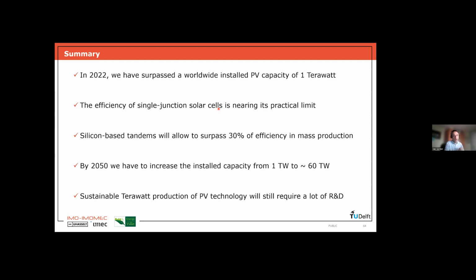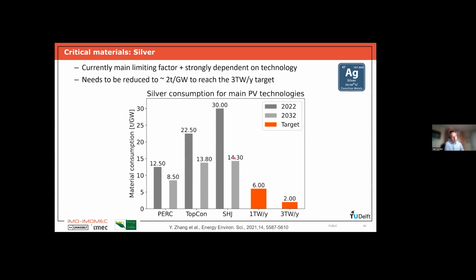Yeah, so that's a good question. But as I've shown in my slides, at the moment, for instance, from the point of view of silver, PERC is actually doing pretty well. And if we compare, because back surface field is not anymore considered in these graphs, because basically it has already faded out. It's really the past. But if we compare aluminium BSF with PERC, I would say the PERC has a much higher efficiency. And because of this, from an environmental point of view, because the cell concepts are pretty similar, so the amount of silver that you need to use and the wafer thickness and so on, it's all very similar. So from an environmental point of view, I think the PERC is for sure going to do much better than the aluminium BSF, because we consider everything from the point of view of how much you need of something and how much greenhouse gases you produce per watt or per gigawatt.